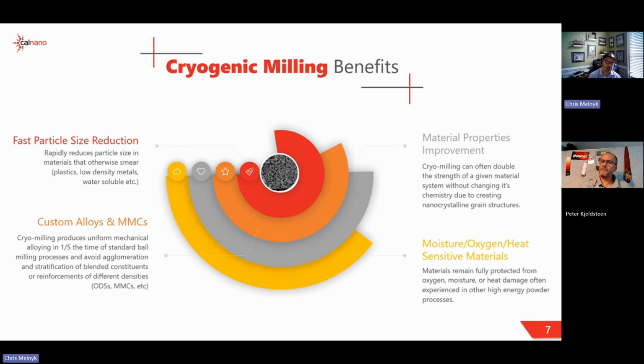The reason for that would be, again, remember that coating I mentioned? Not every material does that. So for the materials that coat, the answer is more of a no. And there's two reasons for that. Because we do a break-in run, we call it, and it's essentially like a seasoning. So we start off with the mill fully cleaned, everything's fine. Then we put that coating inside of the mill, and then the excess material that's in there is discarded, and that's the break-in material, and that would be your contaminated material.